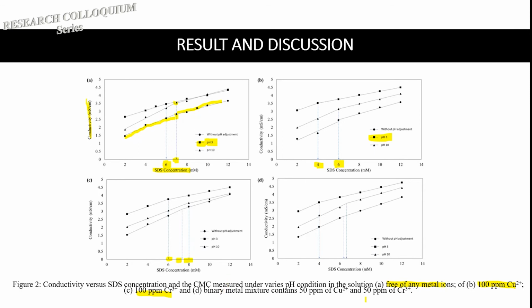And lastly, it's quite interesting that when we put in a mixture of 50 ppm of copper and 50 ppm of chromium, we realize that at pH 3, the CMC is around 4 millimolar. It is quite comparable to our second system, which has only copper. And then without any pH adjustment and at pH 10, we realize that the CMC does not deviate that much compared to the system that contains only copper.